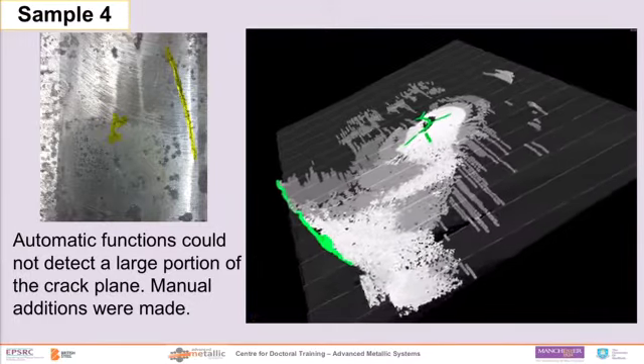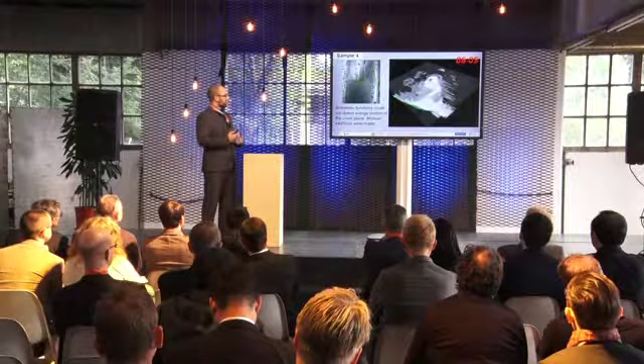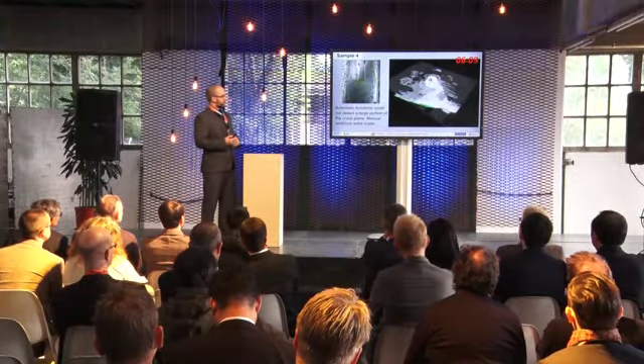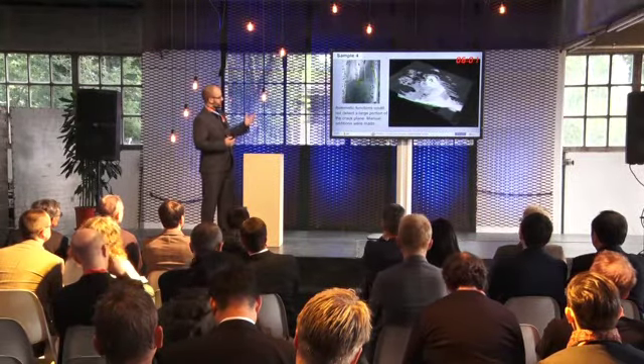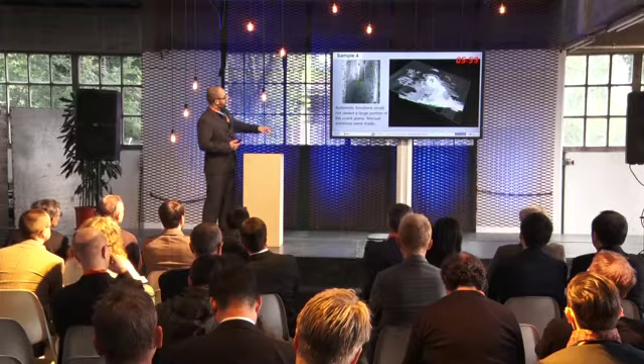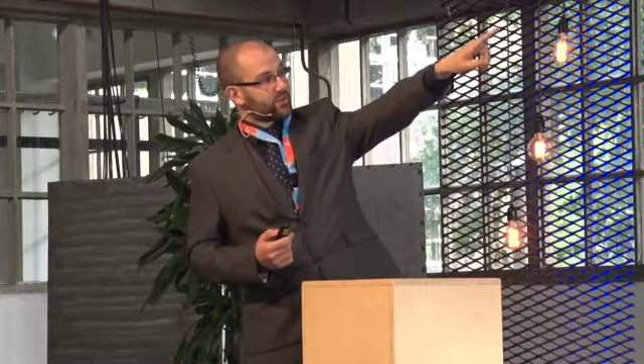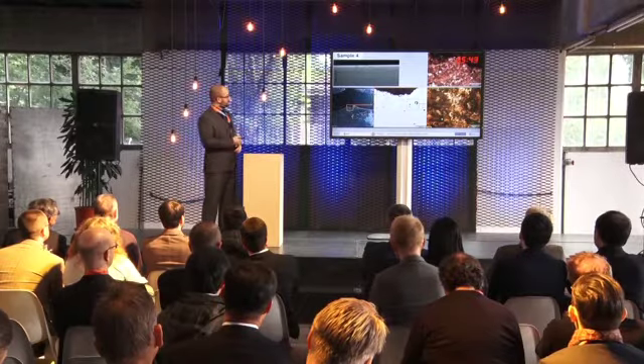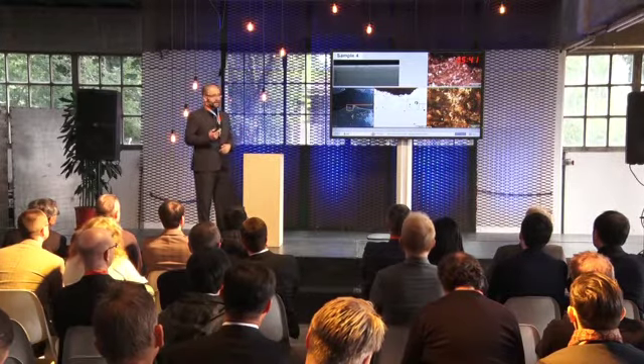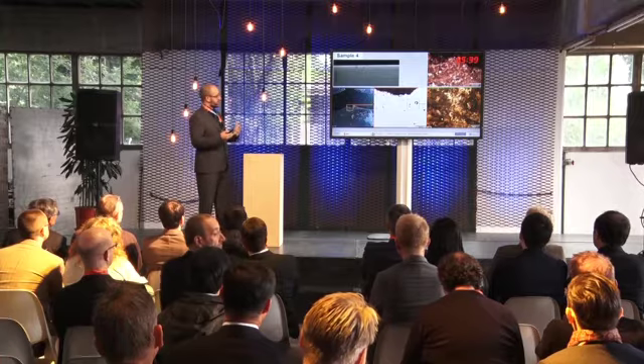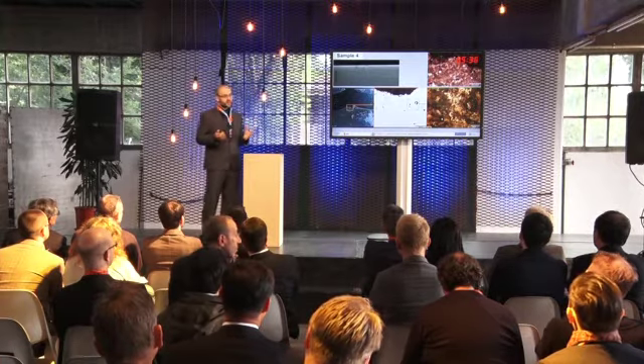But generally speaking, these defects are somewhat simple in terms of it doesn't branch much, and that would probably just end up shelling away eventually. The initiation site, which is towards the centre, which again correlates to the yellow, is on the very edge of the weld. So that's something I took an interest in because I believe this was the initiation point, with the other crack just being where the crack broke out on the edge. So looking at the initiation site, I did do a hardness map to try and see if there was a very big hardness variation.